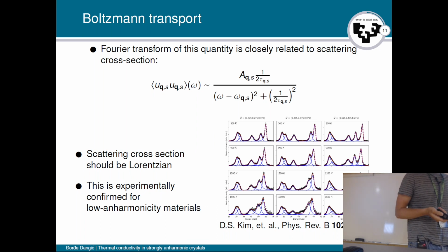And this is true for low anharmonicity materials. So here we have a figure from this reference. I think this is silicon, which is a highly harmonic material. So the anharmonicity is quite low here, and this is a high quality sample, so this picture is valid. And as we can see, these peaks can be fitted almost perfectly with a number of Lorentzians, right? So in silicon, we know that this picture holds, and this has been proven by numerous first principles calculations that predict lattice thermal conductivity in silicon quite well.